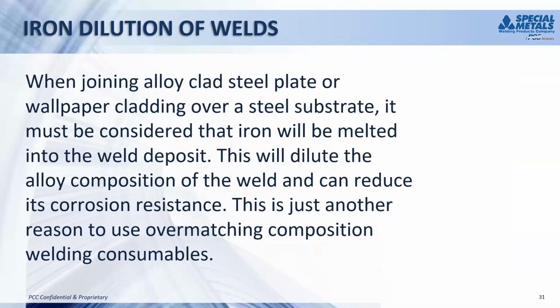In Brian's presentation about cladding, he mentioned iron dilution, and we can encounter that same problem in FGD systems if we're welding alloy clad steel plate or in the wallpapering technique. In either of those cases, there's potential for dilution of the weld with iron from the substrate. To avoid that, obviously we want to use a procedure that minimizes the iron dilution, but if it does occur, we would suggest the use again of an overmatching composition filler metal to counter that iron dilution. That way, even if some iron does get into the weld, it still has full corrosion resistance.